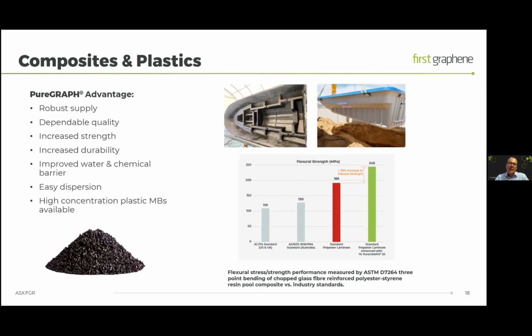The standard laminate, the standard composite, is the red bar. You can see that it easily meets the standards, but by adding graphene, we get an immediate 30% improvement in strength, which is the green bar. So this enables the use of less material and lightweighting in all of these systems.